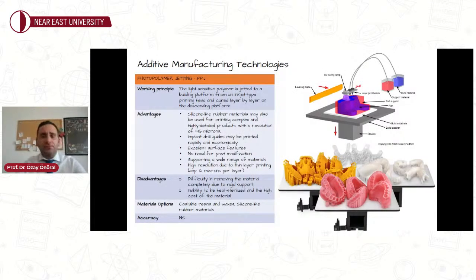The technique that I want to mention to you today is photopolymer jetting. In photopolymer jetting, the light-sensitive polymer is jetted into a build from an inkjet printing head and cured again layer by layer on the descending platform. The most outstanding feature compared with the technologies I have described is that you can produce rubber-like materials like silicones, with a resolution of 16 micrometers, and this makes photopolymer jetting the best candidate to be used in the fabrication of maxillofacial prostheses.